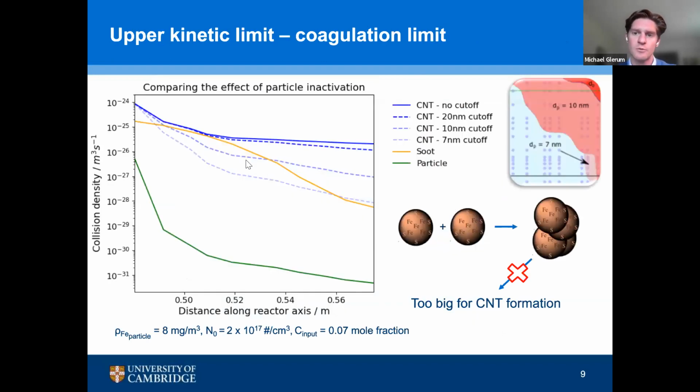So this particle coarsening zone actually constitutes an upper kinetic limit for the coagulation of your aerosols. What we see here is that you could endlessly put in more and more iron, and more and more carbon. But in the way that carbon nanotubes form, the predominant thesis for that mechanism results in there being a diameter-dependent limit for our CNT formation.